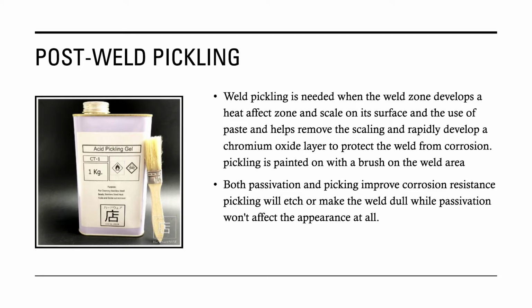Weld pickling is needed when the weld zone develops a heat affected zone and scale on its surface, and the use of paste helps remove the scaling and rapidly develop a chromium oxide layer to protect the weld from corrosion. Pickling gel is painted on with a brush on the weld area. Both passivation and pickling improve corrosion resistance. Pickling will etch and make the weld dull, while passivation won't affect appearance at all.